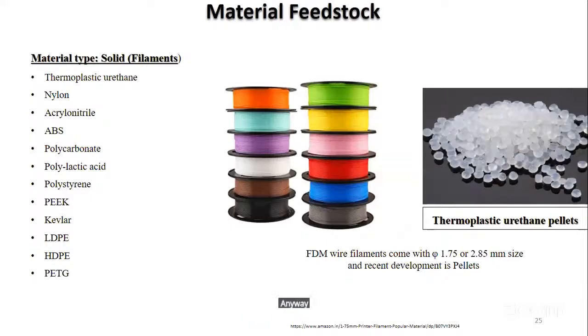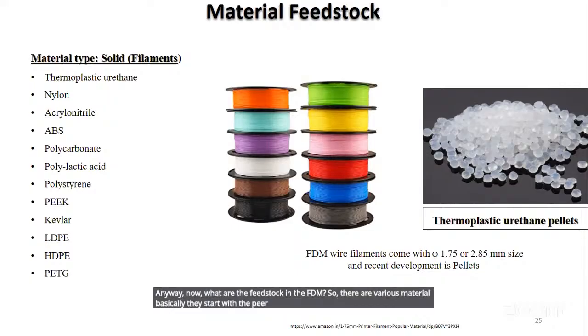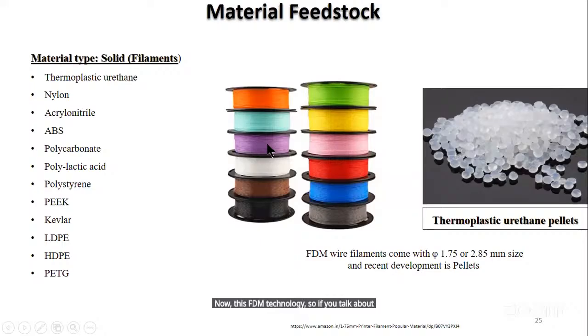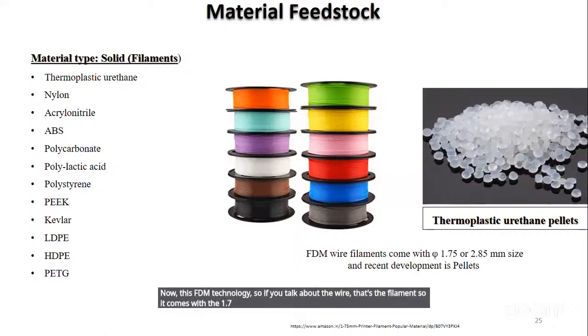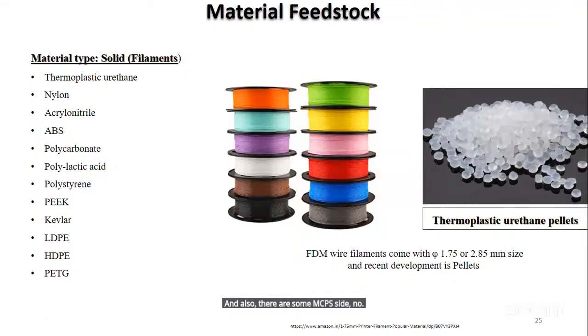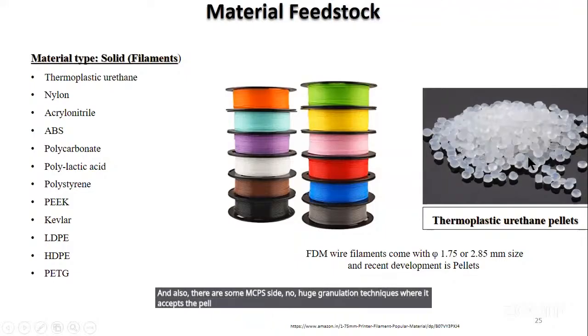Now, what are the feedstocks in FDM? There are various materials. Basically they start with PLA and ABS, which are commonly used nowadays also. But apart from that, you have PEEK, Kevlar, and carbon fiber, whatnot. Plenty of materials are available as feedstock for this FDM technology. If we talk about the wire, that's the filament. It comes in 1.75 or 2.85 millimeter diameter, based on the machine you have. Also there are FGF, as I said, fused granulation techniques, which accept pellets. The pellets will be fed from the top, and the rest is the same as in the filament machine.